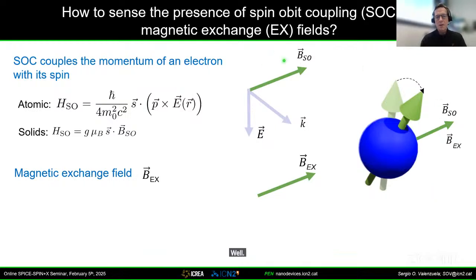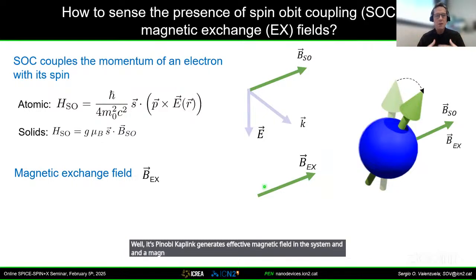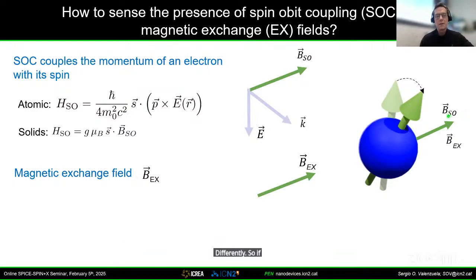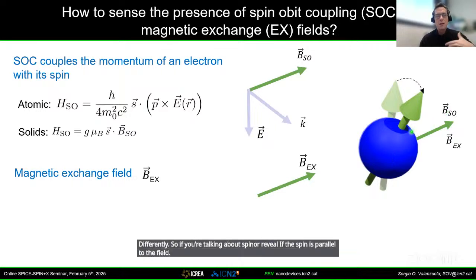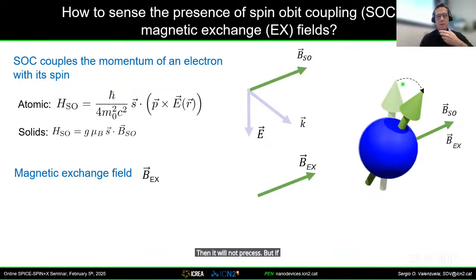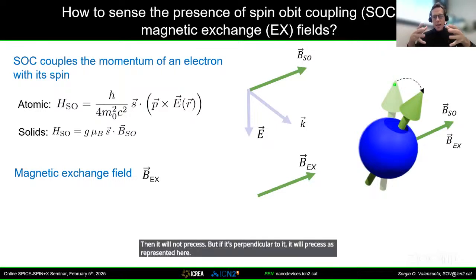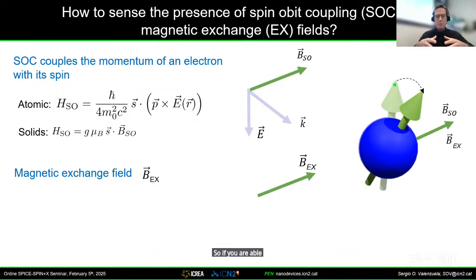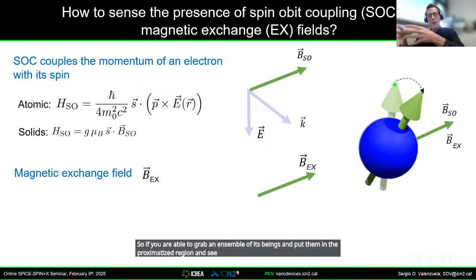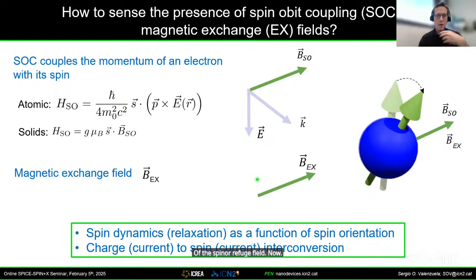Well, spin-orbit coupling generates an effective magnetic field in the system, and the magnetic exchange field also generates an effective field in your system. Under the influence of these exchange fields and spin-orbit fields, the spin will behave differently. So if you're talking about a spin-orbit field, if the spin is parallel to the field, then it will not precess. But if it's perpendicular to it, it will precess, as represented here. So if you are able to grab an ensemble of spins and put them in the proximitized region and see how they behave with different orientations, then you will be able to say something about the orientation and the magnitude of the spin-orbit field. Now, this is going to be the way we are looking into the problem.